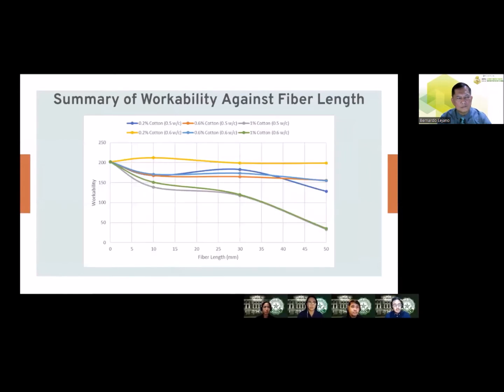Based on the graph, the 0.6% amount of cotton yielded the best results when it comes to achieving the target slump. Therefore, this was used for stage 2. And as for the water to cement ratios, the 0.6 water to cement ratio was adopted for the concrete cylinders for stage 2, as this showed the higher workability.